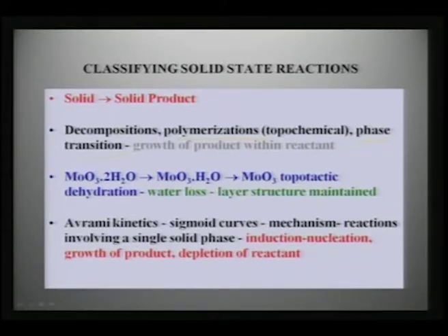One of the classic examples of this sort is taking molybdenum trioxide, which is usually a dihydrate, and if you heat this it transforms to a monohydrate and then it goes through a topotactic reaction to give MoO3. The beauty here is that it is a topotactic reaction involving water loss, and this can be monitored based on Avrami kinetics. We can talk here about the single solid phase interaction where induction, nucleation, growth, product and depletion of reactant can be studied at one stretch.